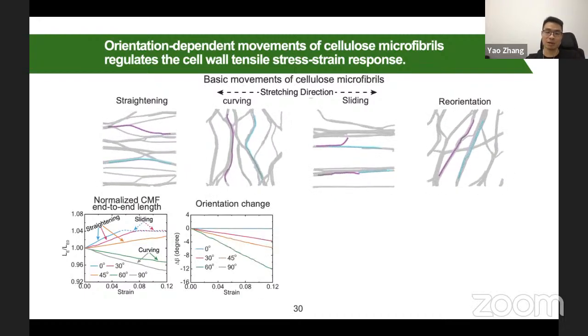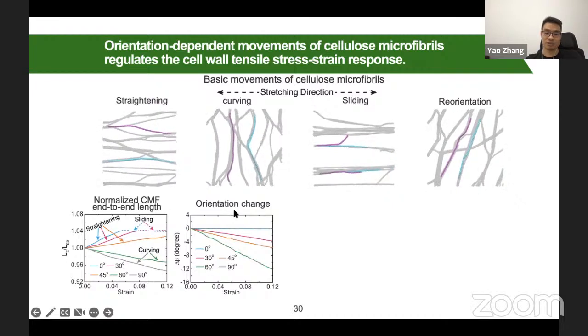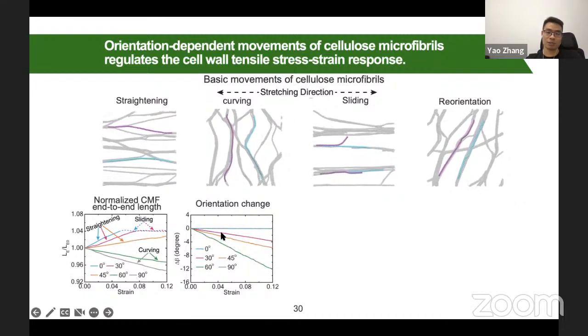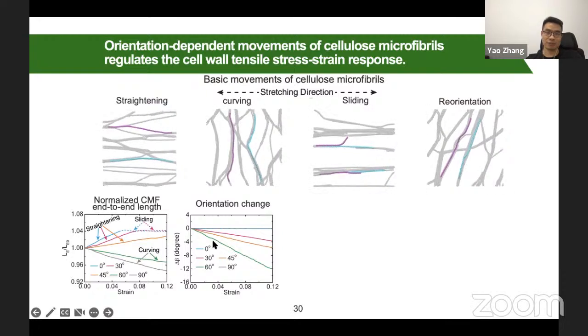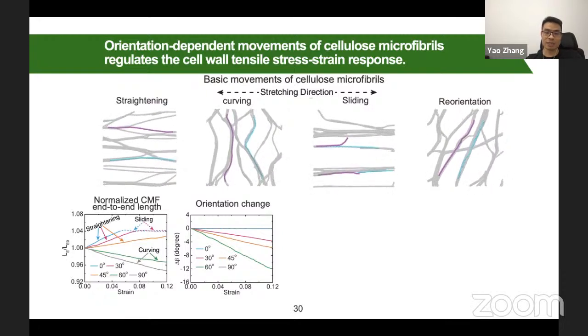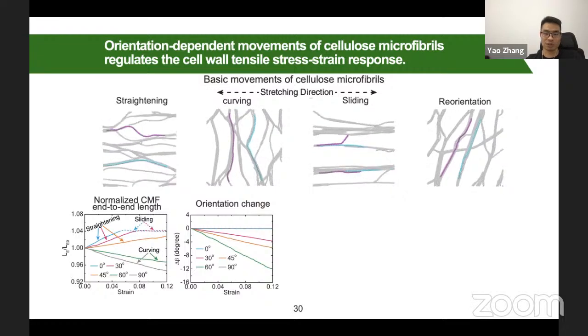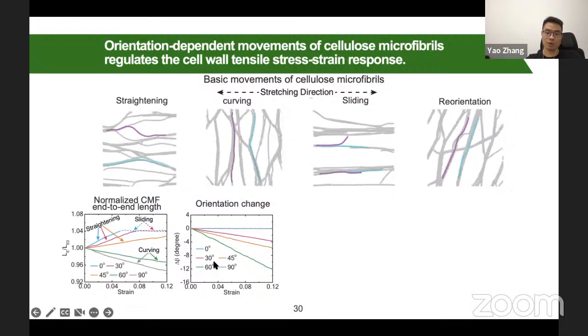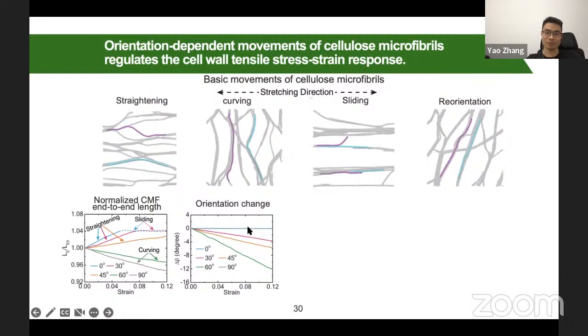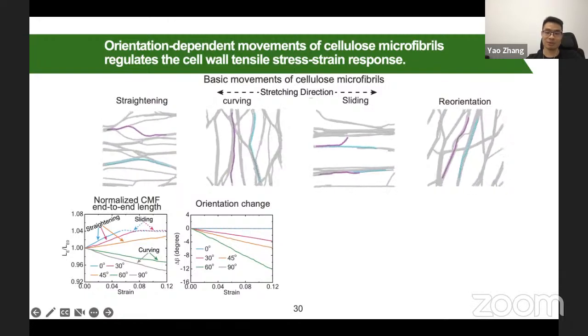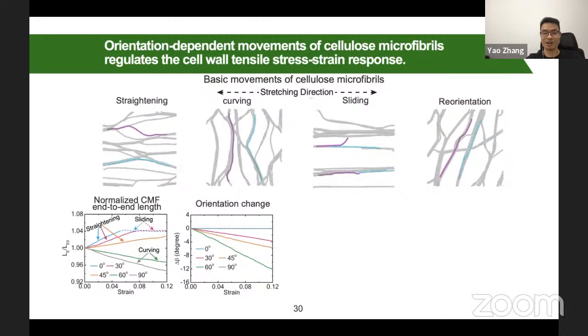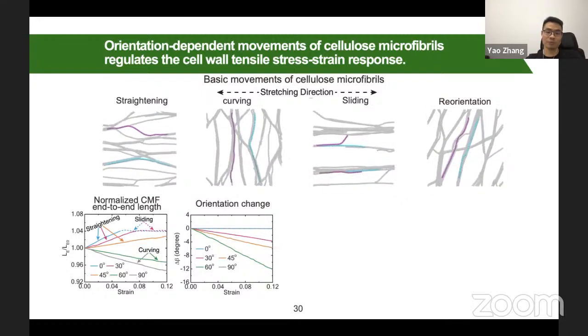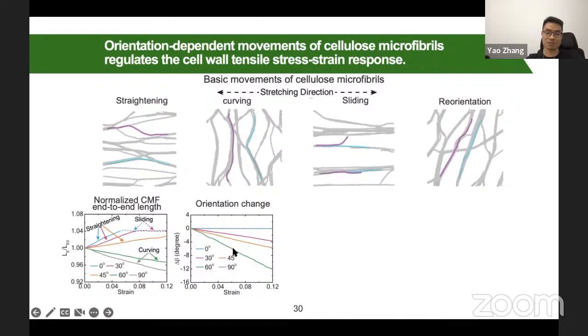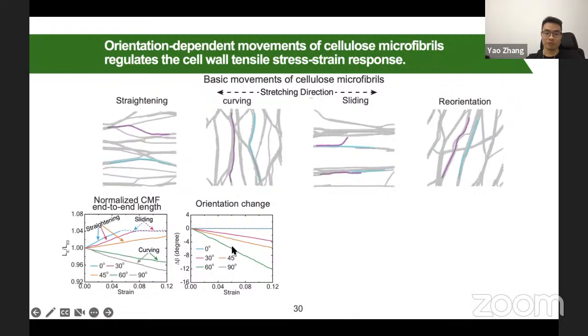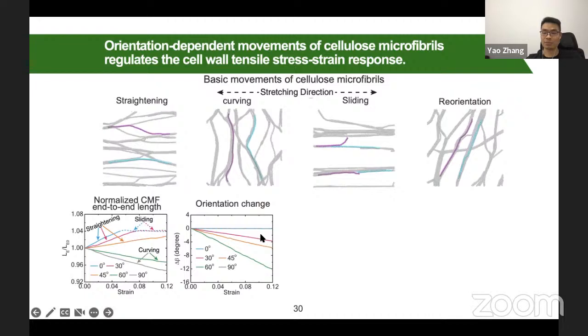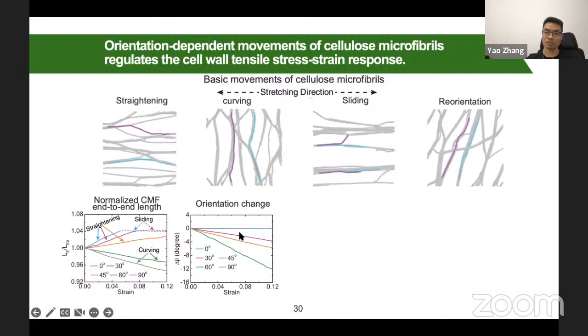And we also check the orientation change. You can see that the lamellae have different orientation changes. When you have an orientation of 0 degree or 90 degree, you don't see the orientation change. If your cellulose orientation is between 45 degree and 60 degree, that has the maximal orientation change.